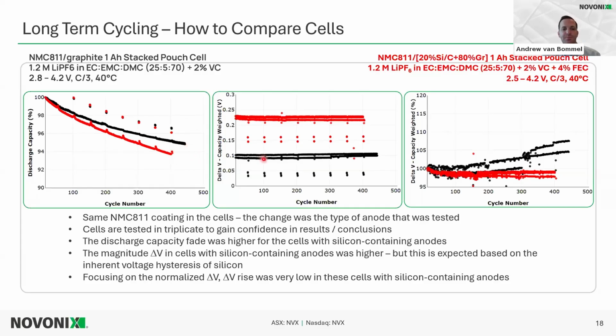When we look at the delta V, again, as I cautioned when looking at the magnitude of the delta V, as expected, since there's inherent voltage hysteresis from silicon materials, if we look at a coin cell of that silicon-carbon electrode versus lithium, we would see that voltage hysteresis is much higher than in graphite alone. So we expect that delta V to be higher in that silicon-containing material. If we look at the normalized delta V, we in fact see that the delta V rise is relatively low in those cells containing silicon-containing anodes. So those are very promising cells.